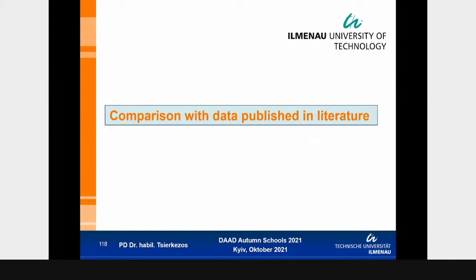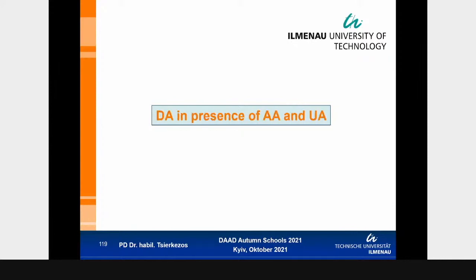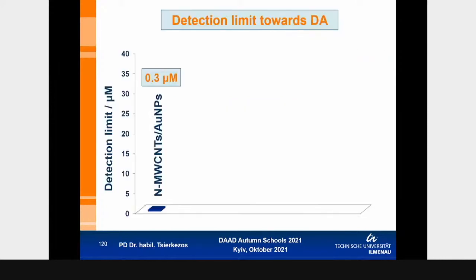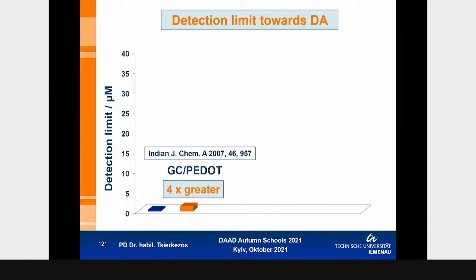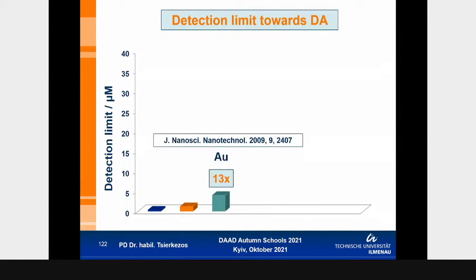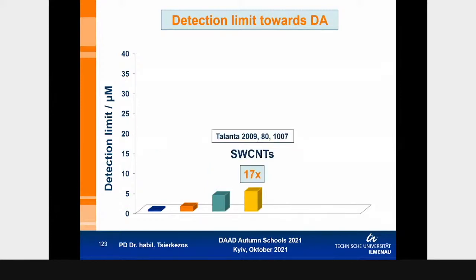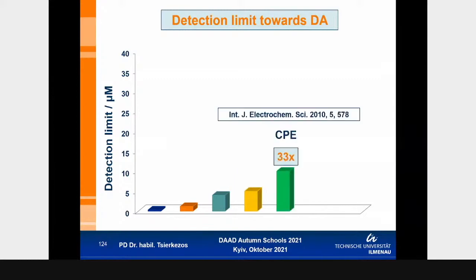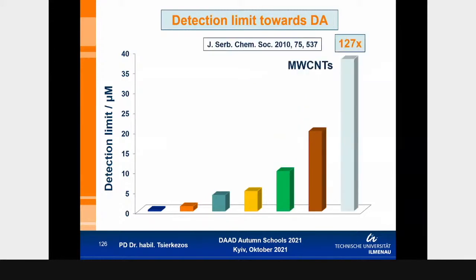Important is also a comparison of the extracted data which we got in our laboratory for our novel sensors with those published in the literature for other novel sensors containing as well carbon nanomaterials and metallic nanoparticles. First, a comparison of the extracted data with dopamine. So our detection limit of dopamine in nitrogen-doped carbon nanotubes modified with gold nanoparticles lies at about 4 times lower compared to other electrodes like classic carbon electrode modified with a polymer, or 13 times better compared to pure gold electrode. It is much better compared to single wall carbon nanotubes or to CPE or other standard electrodes.